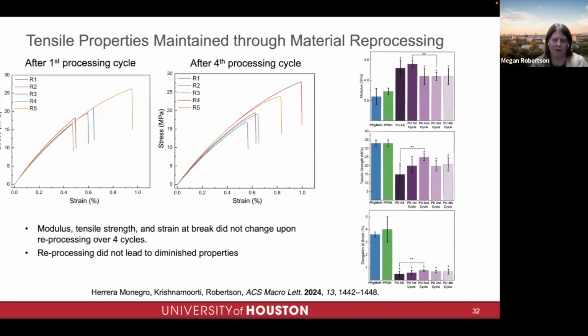And finally, the whole point of adding this catalyst was not only to make the materials such that we can easily melt extrude them through the way that we formed the urethanes, but also so that after the end of life, they could be reprocessed. We did a little test of this by looking at how many times we can recompression mold our sample. We just chopped up the test bars into pieces, compressed them together in compression molding equipment, and tested the tensile data again, and we basically didn't see significant changes in their properties upon reprocessing over and over.